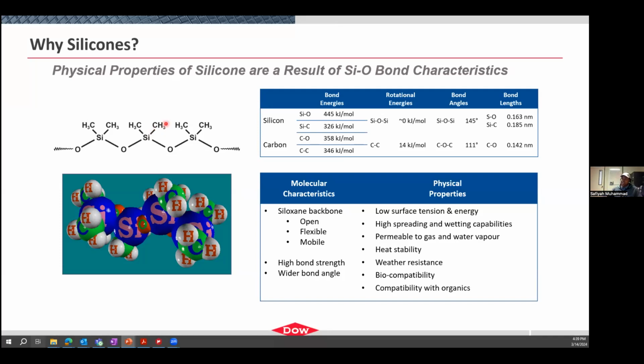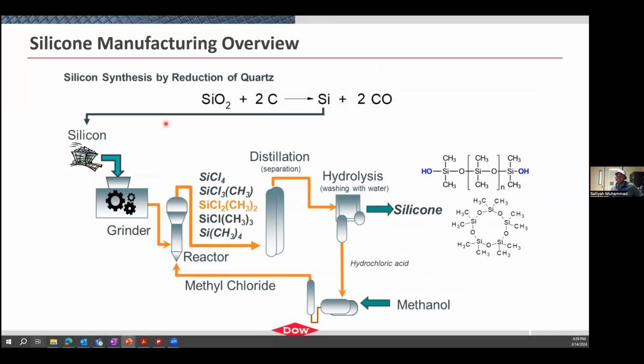So how do we make silicones? It actually starts from quartz. Quartz is a crystalline version of sand. We mine quartz, and then you can cook it with a carbon source so that you remove the oxygen and purify silicon metal that you can find on your periodic table. And we take those hunks of silicon metal. I used to have a piece on my desk, and I've lost it at an outreach activity. But you can take these hunks of silicon metal and grind them down to a very fine powder.